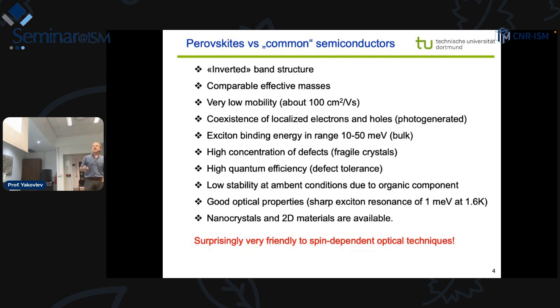So this is a list of the differences and common things when I compare perovskites with common semiconductors. We have the inverted band structure, already discussed. Effective masses are rather comparable, in GaAs and perovskites, on the same level. What is really different is the very low mobility. Of course, when I came five years ago to a conference on perovskites, I was shocked, because every second talk was about the giant mobility of the perovskites, a number of 100. I was missing the point. 100 million for normal semiconductors is a giant mobility, but not 100. And I was told that the field is very much originated, populated and driven by people from organic semiconductors, for whom 1 is large, 10 is huge, and 100 is colossal. So it's a very different scale.